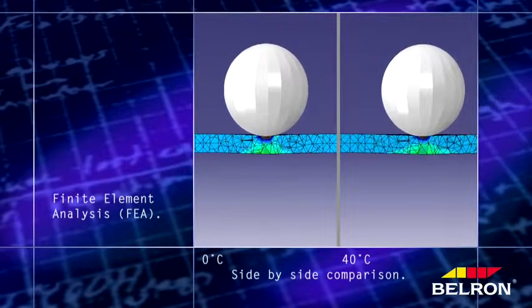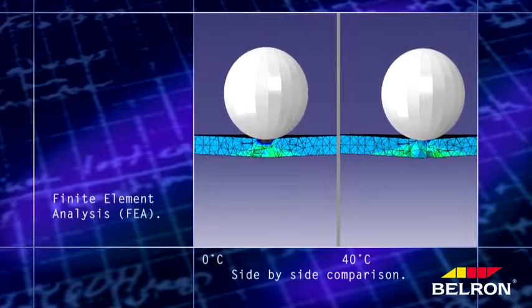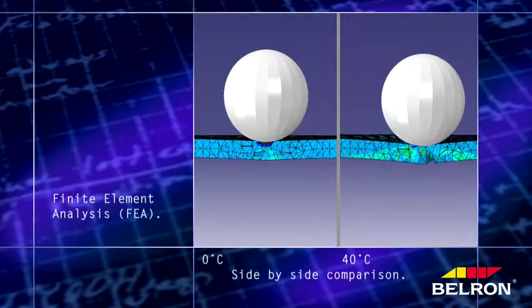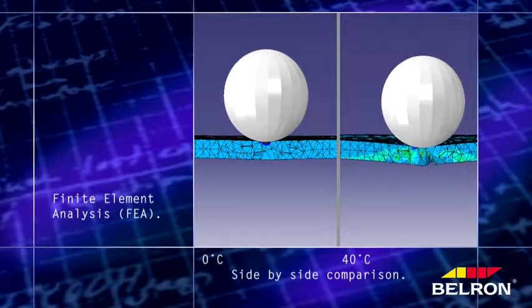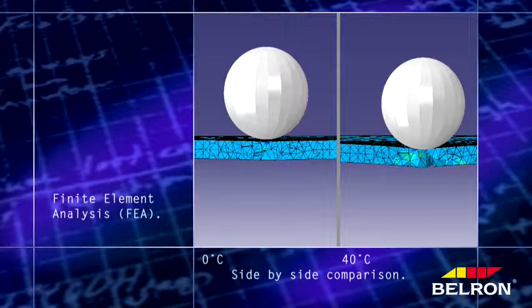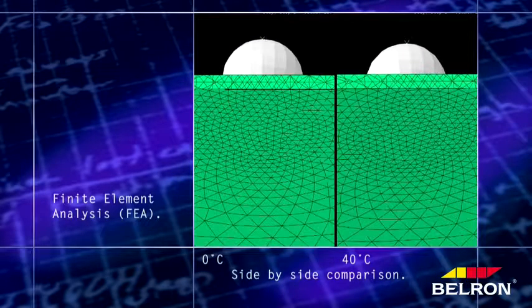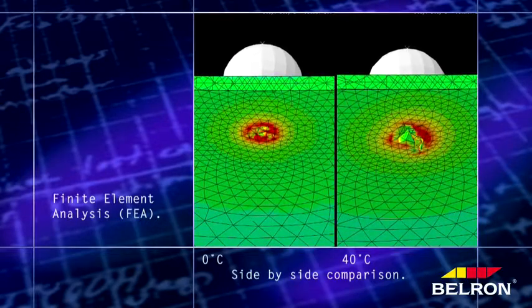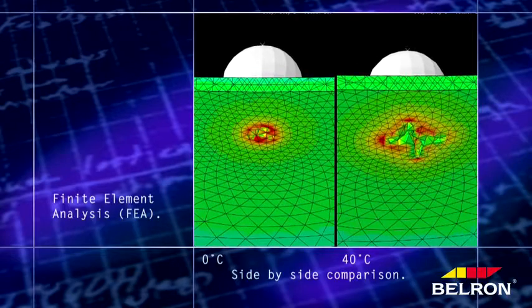When it's cold, the interlayer is stiff and the laminated windscreen behaves like one unit, resisting the impact, bouncing the stone right back, if you like. But when it's warm, the interlayer becomes much springier. This disconnects the two glass layers a little and allows the top layer to bend more when hit by a stone. This means the shock wave isn't so well dissipated through the whole windscreen, and the chip is therefore bigger.